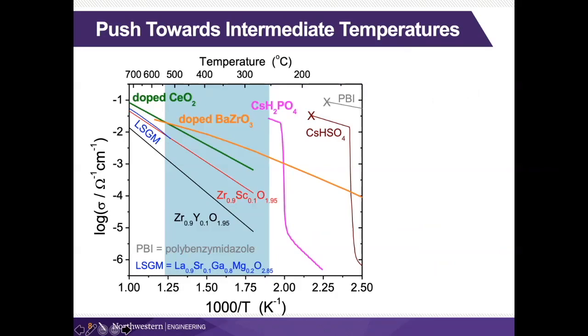Okay. So there's a push towards intermediate temperature. That's sort of the race to the middle. All puns intended. So what we have here are the conductivities of a number of different materials. And let's say we want to operate at somewhere between around 250 and maybe 550 degrees Celsius. And we have here doped barium zirconate, which has a very high conductivity in this range. There's also doped ceria, which is a fluorite structured material, which has very high conductivity as well.